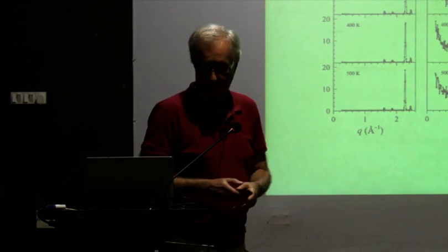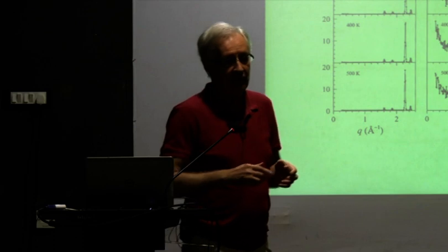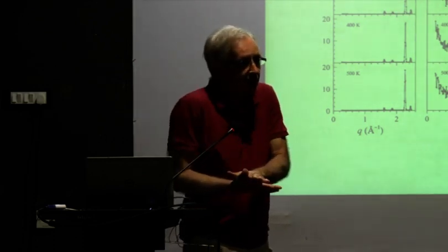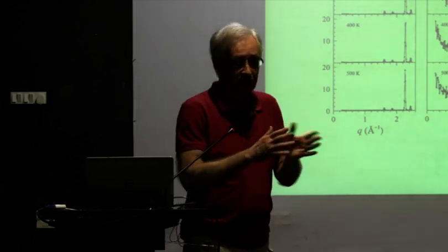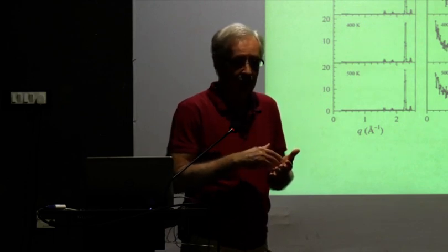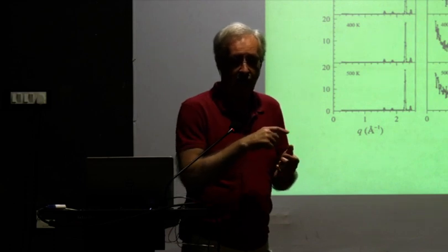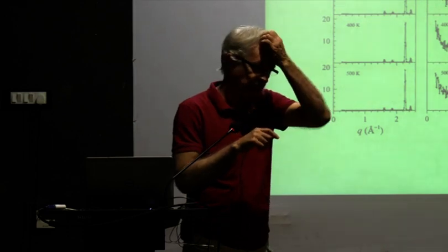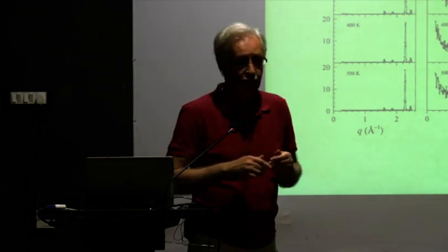There are no domains, and the fact that there are no domains and that perhaps there is not much volume change between the two systems tells us that this system is rather unstrained, so that when we apply a magnetic field and look at the magnetization, the curves retrace and so on. Increasing magnetization, on increasing field and decreasing field, the magnetization curves follow one another, and we lose hysteresis.